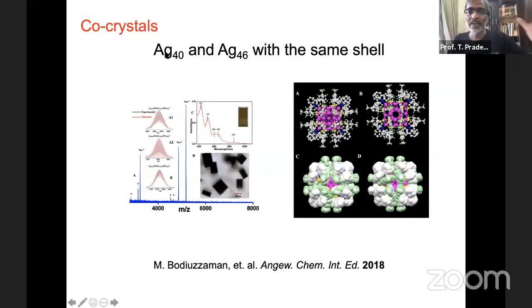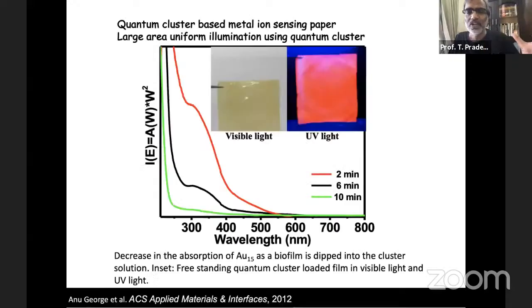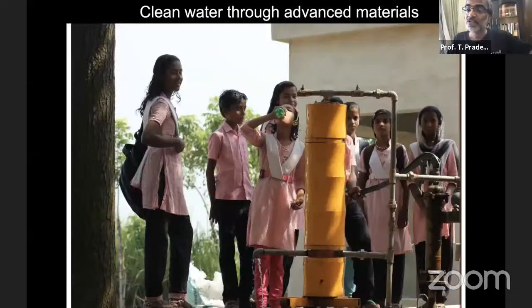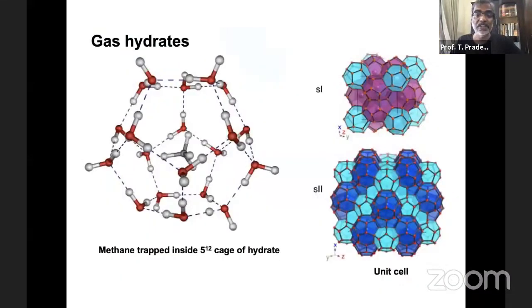So when you have one cluster and another cluster, not only can these molecular crystals be made, A crystal and B crystal, you can combine these. So you can create such co-crystals, essentially giving you completely new properties. What would this give you? You can explore properties. In this particular case, the luminescence of these clusters is explored to create new sensors. And these sensors can, of course, be incorporated into devices of this kind, which are water purifiers, and we work in that area. The other molecular system that in this center we will be interested in is gas hydrates.